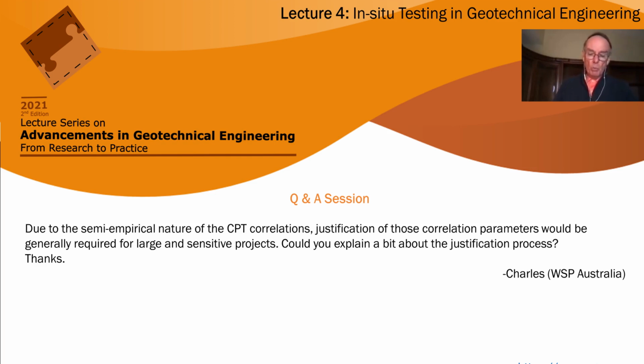And of course, if you measure the shear wave velocity, then that greatly improves it because you're directly getting a measure of the stiffness. Usually you have to soften it down to the strain level that you require for design. Now, I spent a little bit of time in this presentation showing that if you measure the shear wave velocity, you have the ability to identify whether or not there's significant microstructure. Now, if there is significant microstructure, we know that some of the correlations will tend to be off because the material you're encountering doesn't match a lot of the historical material to which the empirical correlations were based.